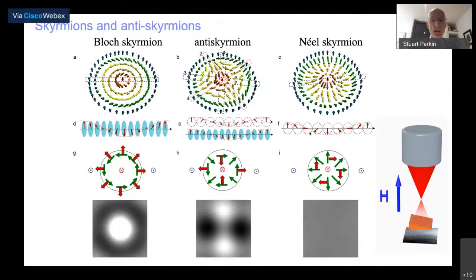So this is basically called Lorentz transmission electron microscopy, and you can see these are the patterns shown in the bottom. On the left side, the Bloch skyrmion looks in the microscope like a single dot, a white bright dot where the electrons are focused. On the right-hand side, the Néel skyrmion, you actually see nothing in the microscope if the electron beam is transmitted perpendicular to the plane of the skyrmion.